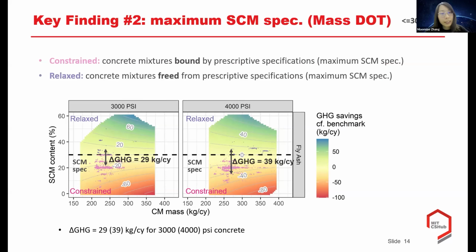We also investigated the actual GHG savings based on the operational data, as shown in the scatters here, and we classified the concrete products into a constrained group and a relaxed group based on the SCM specs. Then we compared the GHG emissions between the constrained and relaxed groups. The average ΔGHG is about 29 kilograms per cubic yard for 3,000 PSI concrete and 39 kilograms per cubic yard for 4,000 design PSI concrete mixtures.